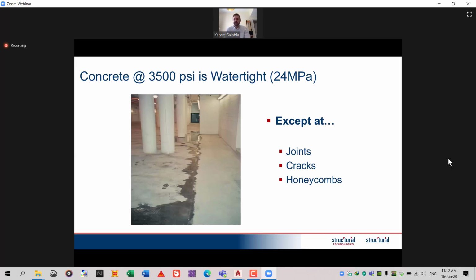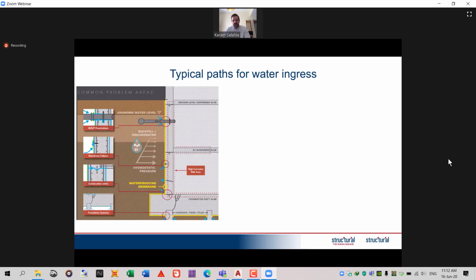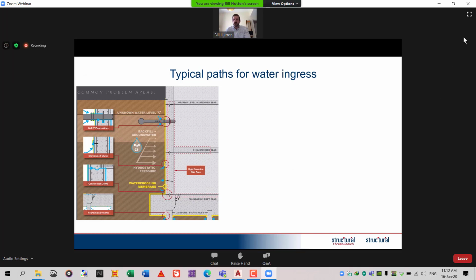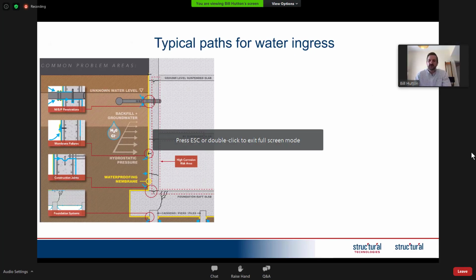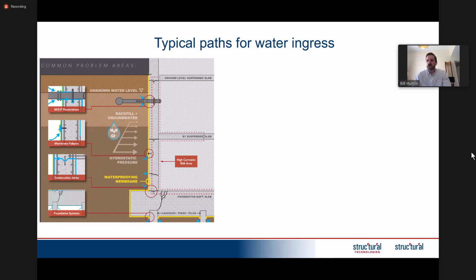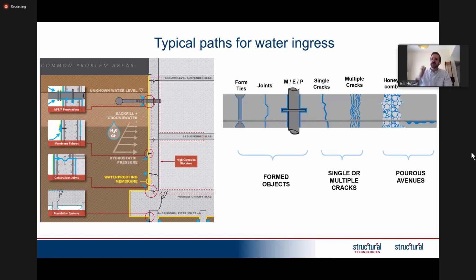So most buried structures, including basements, are constructed with a waterproofing membrane system. So this could be a bonded or unbonded system. And the idea of this, or the design intent of this system, is to prevent water from coming into a building. However, in our experience, more than 70% of these membranes seem to fail in some way or another. And then once the membrane has failed, water is like electricity, and it will just take the path of least resistance into a building. So the pathways could be left in place form ties, could be construction joints, could be MEP openings, could be cracks, or could be porous avenues if you have poor quality concrete or honeycomb.